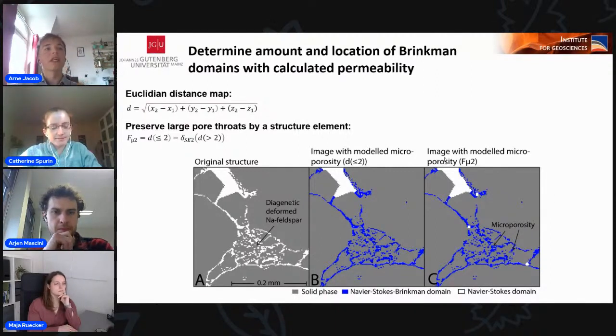But this would have closed larger pore throats with complex topology as well, which is not wanted. So we had to preserve these open pores by a structure element which restores the original shape of the pores. The domains in blue contain the voxel permeability of the illite clays, which were measured by simulating the permeability by applying Navier-Stokes equations.